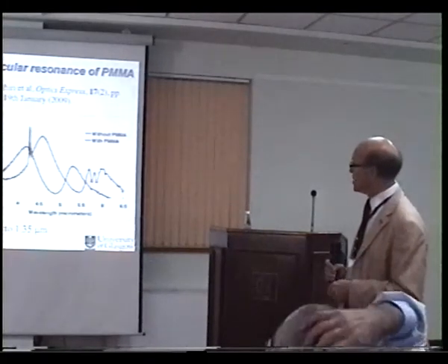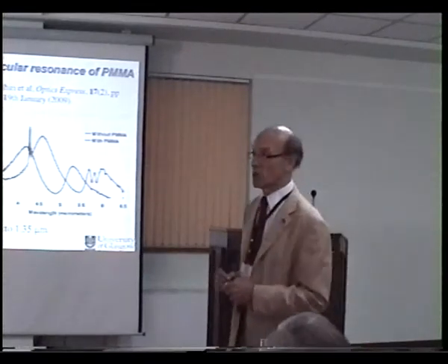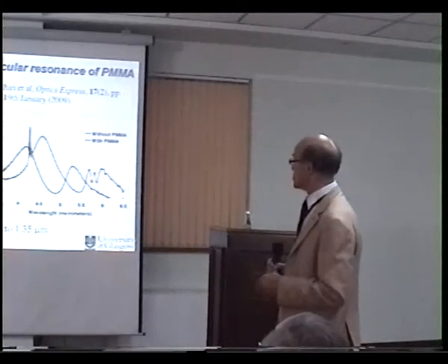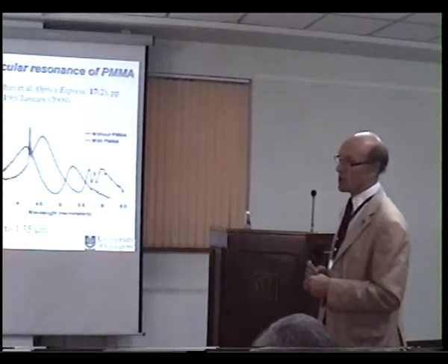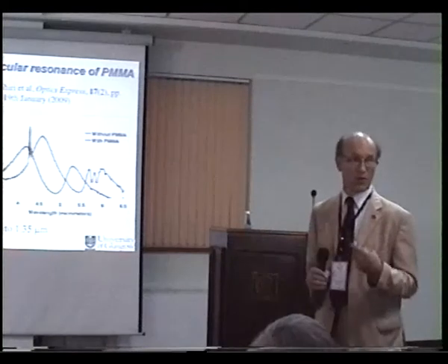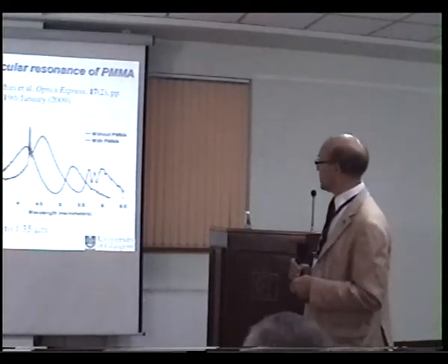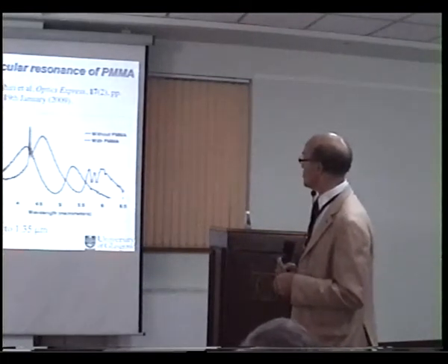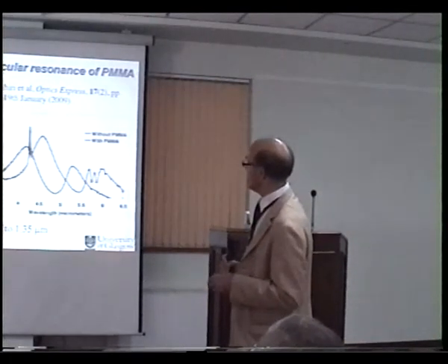But what I've also got on here is what I like to call a super-Fano resonance. It's a super-Fano resonance, which is going up and down characteristically like a Fano resonance does, but it's going up and down several times, which depends on the thickness of the PMMA. So I'm getting a very strongly enhanced interaction near this reflection peak, and it will look quite different if I shift the resonance of this structure with respect to the molecular resonance.